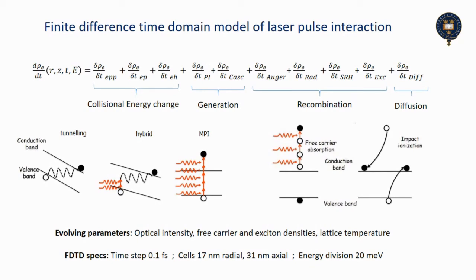Now, what we're trying to do here is to ascertain the number of carriers which are generated and have enough energy that they can relax and create Frenkel defects. And the activation energy for Frenkel defect formation is between 20 and 30 electron volts. So if that's going to be created by a single relaxation event, we have to be involving very hot carriers in this process.